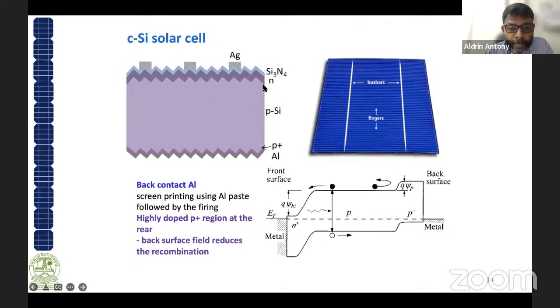You have a P-type silicon, and over that an N-type thermally diffused silicon. And this diffusion is carried out at a very high temperature, something around 900 degrees centigrade. And then there will be another process of silicon nitride, which is a dielectric layer and also an anti-reflection layer. And it serves an additional purpose of passivating the material.